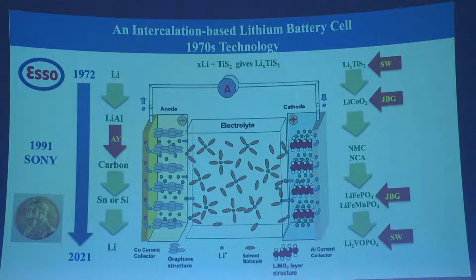So Akira Yoshino then said we could use graphite, and he was working on some cokes at his carbon company and got that to work. The problem with graphite is that you need 72 grams of graphite to store 7 grams of lithium. So there's a huge wastage of weight, and in a lithium-ion battery, half the volume of the battery is that graphite anode. So the goal is to take that out and replace it, ideally going back to pure lithium. But in the interim, we're looking at things like silicon and tin.